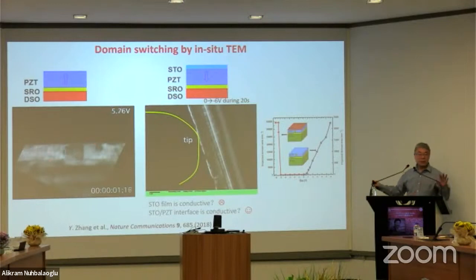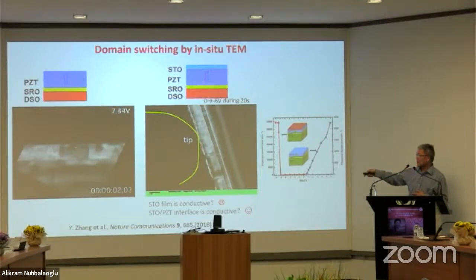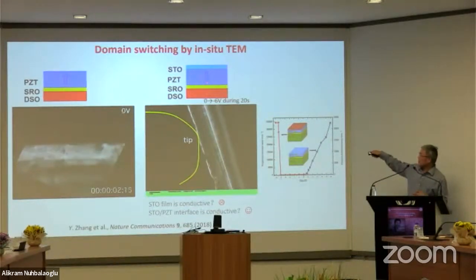So this is our in-situ experiment, and it shows that the interface between ferroelectric and insulator is conducting. This is very well known from the previous example, right? Switching is done with a very small tip. The field is strong here, and the domain first nucleates and then grows further. It's a reversal only.